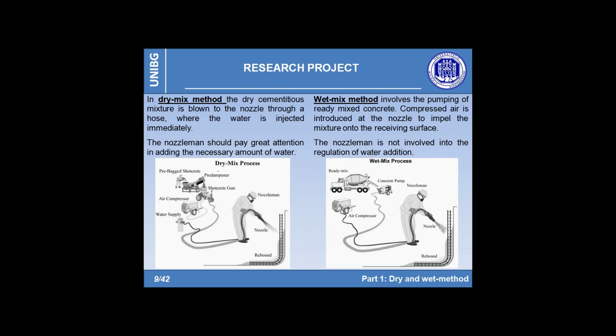To avoid uncertainties, a wet mixed method has been adopted. It provides for the pumping of pre-mixed cementitious composite, hence already mixed with the water in a storage container before entering the nozzle. In this way, the worker cannot compromise the mechanical characteristics of the final product, not being involved in the control of water addition. In fact, the mixture goes out through the nozzle thanks to the compressed air that permits the shooting on the EPS panels without any additional operation. That results in a material whose mechanical properties are stable, replicable, and guaranteed.